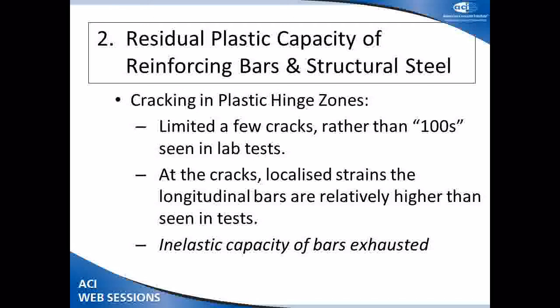The next question, following on from this, is what is the residual plastic capacity of our reinforcing bars and our structural steel? As I mentioned earlier, we're not getting thousands of flexure shear cracks. We're only getting two, three, or four cracks where all the deformation is concentrated. The other factor is that there are very, very high localized strains in the bars either side of those small numbers of cracks.